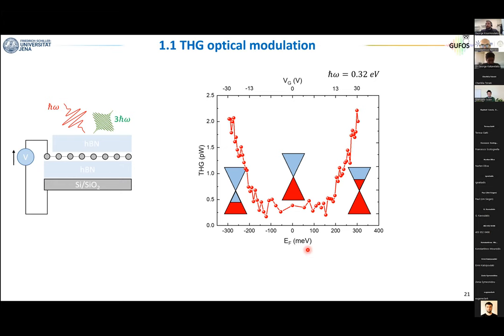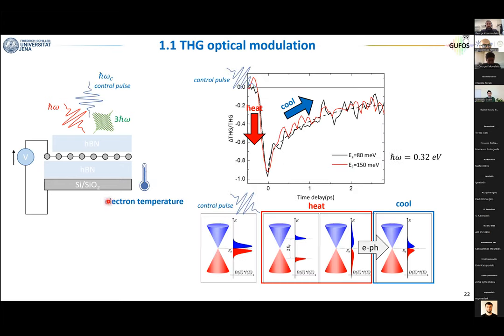But now let's move to the all-optical modulation. Now the idea is the following. We use the gate voltage to fix the Fermi energy, and then we arrive with the control pulse. And now I plot here on the y-axis how much I'm changing the third harmonic. This graph is normalized because I only want to focus on the dynamics. And on the x-axis, I have the time scale, so the delay between the control pulse and the fundamental beam. So time zero means the control pulse arrives together with the fundamental beam.